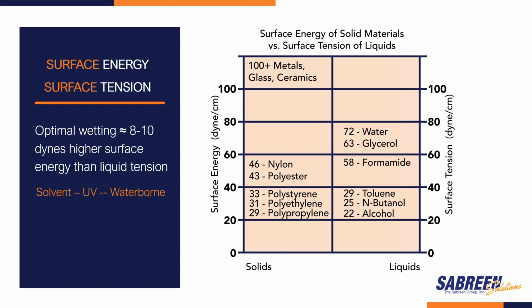We look at several polymers: polypropylene, polyethylene, polystyrene, and nylon. The general rule of thumb is that optimal wetting is going to occur approximately 8 to 10 dynes higher in surface energy than the liquid tension, and one needs to take into account what type of solvent is being used, whether it's a UV or waterborne system.